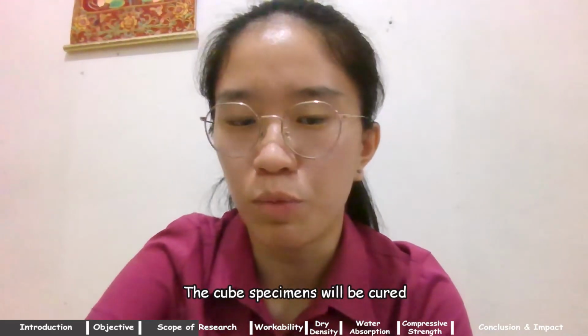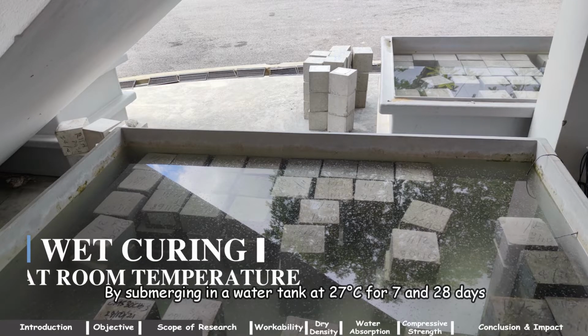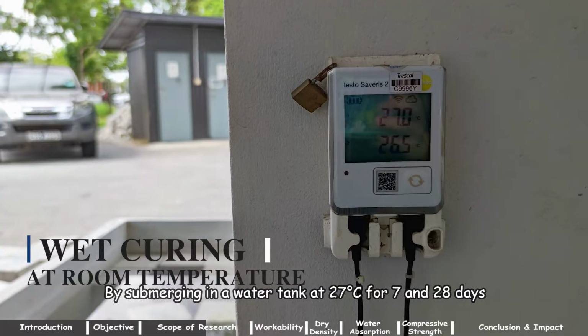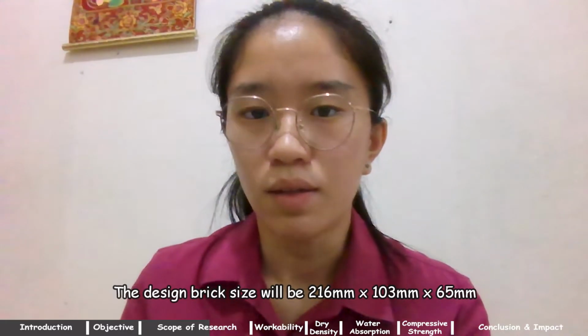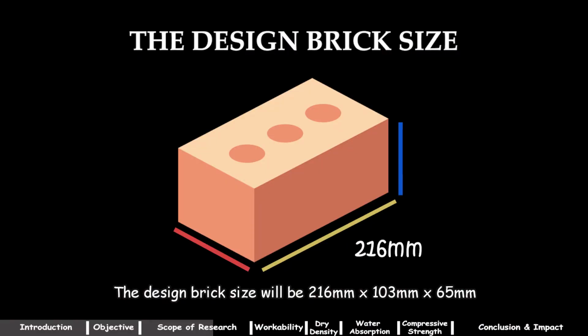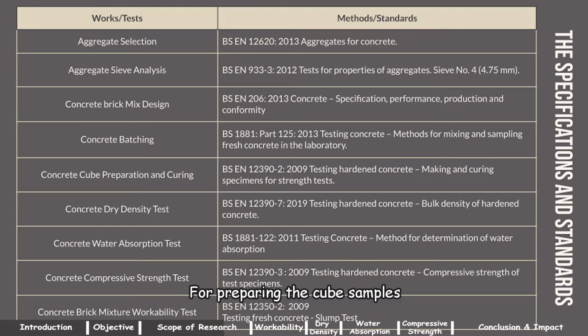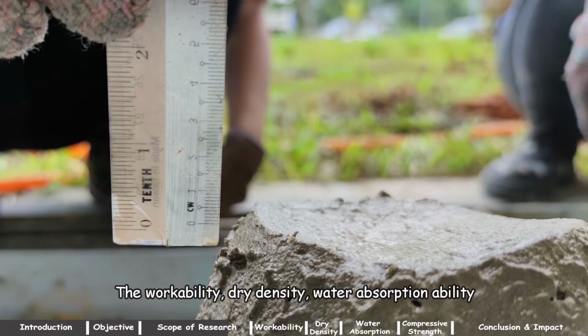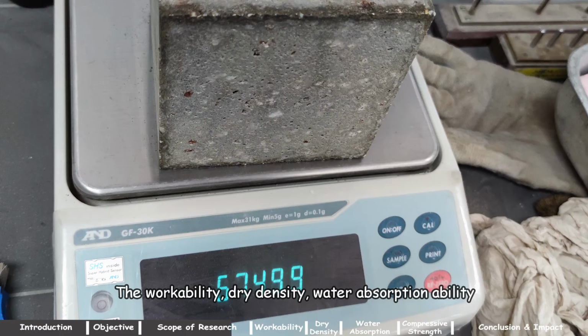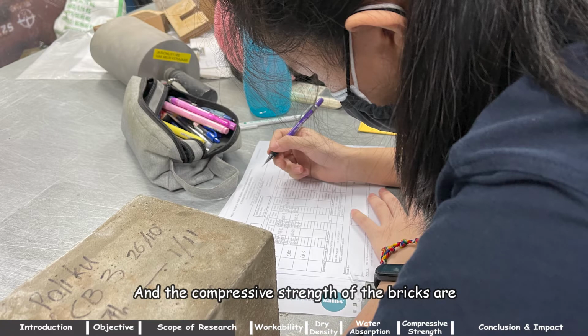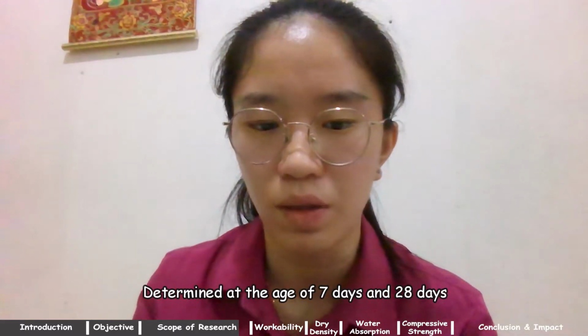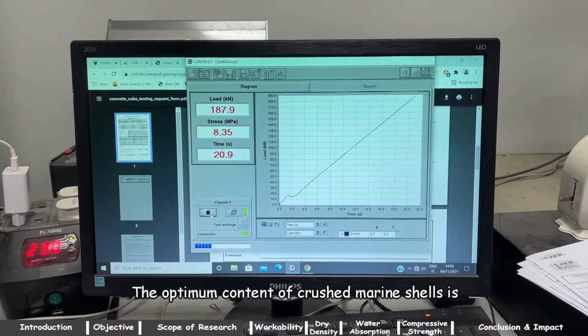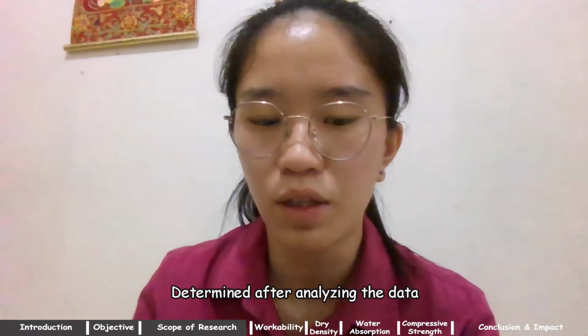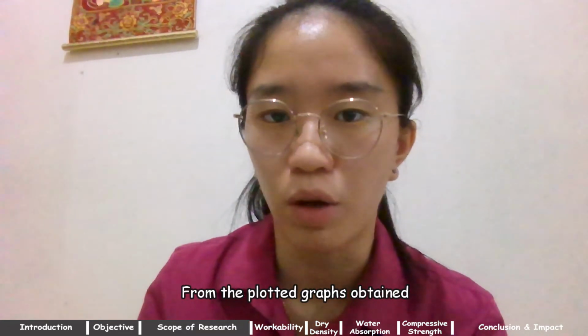The cube specimen will be cured by submerging in the water tank at 27 degrees Celsius for 7 and 28 days. The design brick size will be 260 mm by 103 mm by 65 mm. British standards is used as reference for preparing the cube samples. The workability, dry density, water absorption ability, and the compressive strength of the bricks are determined at the age of 7 days and 28 days. The optimal content of crushed marine shells is determined after analyzing the data from the plot graph obtained.